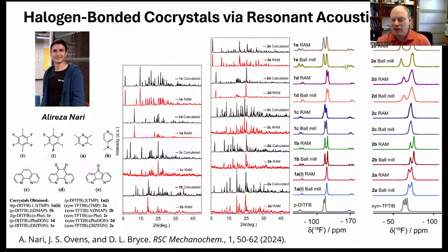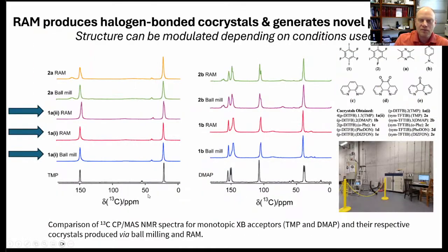There are a couple of interesting traces where we see some differences. So for example, if we look at 1C, the ball mill gives this trace, RAM gives this trace. So this may be attributable either to a different polymorph being formed, or perhaps some impurities left over. If you look carefully at some of these traces, maybe on the next slide, I'll show you, there are some differences in the crystallinity that we can pull out from the RAM products versus the ball milling products.